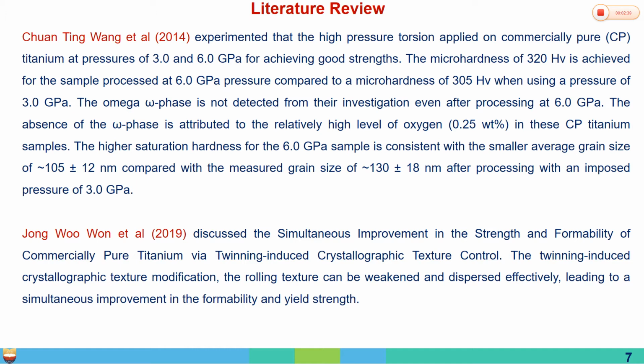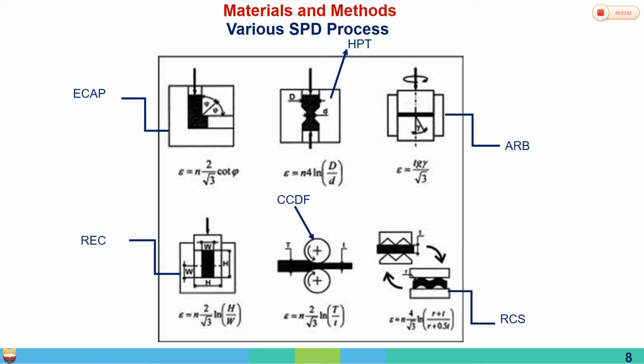The summary of this literature is that the strength of commercial pure titanium was increased by grain size reduction or grain refinement, by adopting different severe plastic deformation techniques. So from this literature we came to know that severe plastic deformation increased the strength of the material, and also increased the tensile strength of the material by grain refinement and grain reduction techniques.